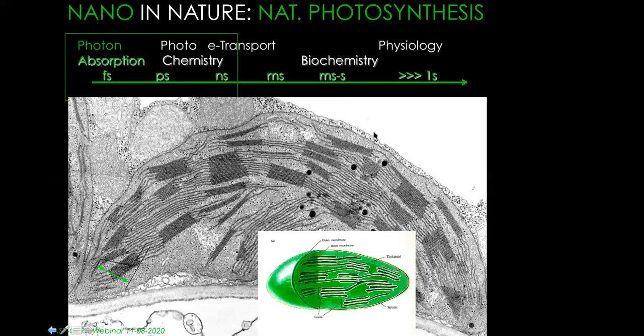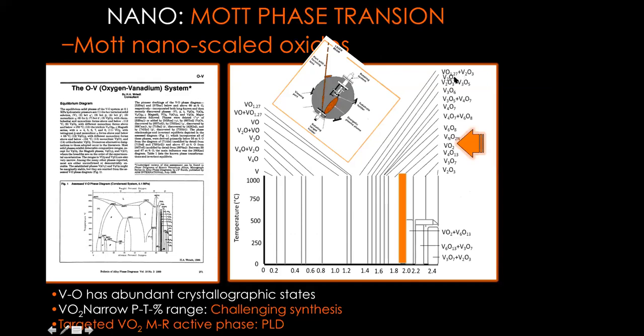Correct. Vanadium has a valence of 5, and therefore it has a huge amount of oxides, as you can see in this phase diagram. A huge amount of stable oxides, and V2O5 among them, of course. And the one which has this very nice phase transition is VO2. You'll find it only in this range, and it's extremely difficult to stabilize. But now we know the tricks, because we worked on it, and the community worked on it also. But VO2 has that Mott transition. Other oxides have it too, but their transition is far above room temperature.